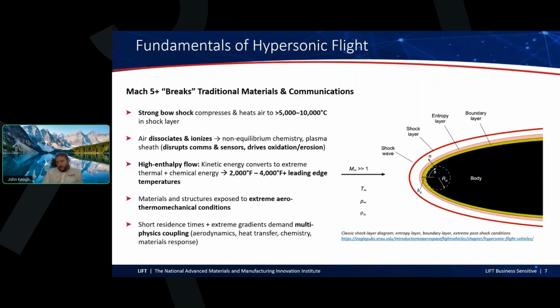And generally speaking, beyond the bow shock, on the leading edge or against the surface, you have this high enthalpy flow. Enthalpy is really just an idea of energy, right? Heat. Effectively, how much heat is in that local environment. And of course, you can discuss heat transfer and heat management, which is where we get into materials design and systems design. But either way, that kinetic energy imparted in the bow shock ends up against your surface, and a lot of that is converted into heat, so you have extreme temperatures and extreme chemical energy. Your surface temperatures, and the leading edges in particular, can often get up above 4,000 F or more. I'm sorry for mixing units, but it's a very aggressive environment. So the materials and the structures are exposed to what we like to call extreme aerothermal mechanical conditions.